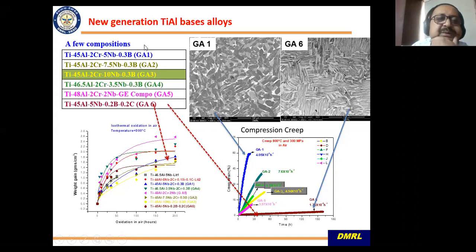And here we had studied certain alloys which are listed here, and these are GE compositions which GE has used already, that is 48Al2Cr2Nb, and we have studied the oxidation resistance and also the creep. So one of our alloys is giving very good creep properties, which is basically GA5, this composition, and this composition has intermediate oxidation resistance, but creep is very, very good. So we have to evaluate other properties like fatigue and all, and then we can go for usage.